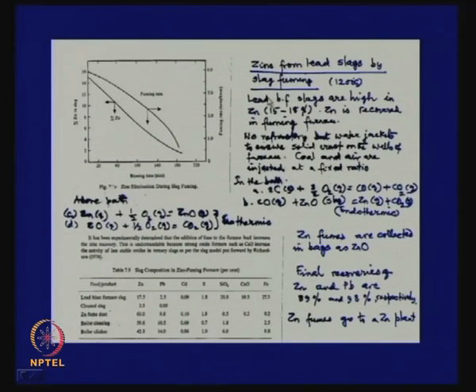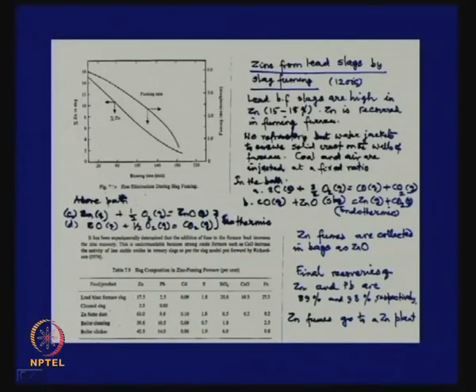Now, we employ a process called the slag fuming process at about 1200 degrees centigrade. In water jacketed reactors, no refractory, but water jacketed for reasons I do not clearly understand, but if you have a water jacketed reactor and it is water cooled, then there is always a frozen solid crust all around, which acts like the protective refractory.